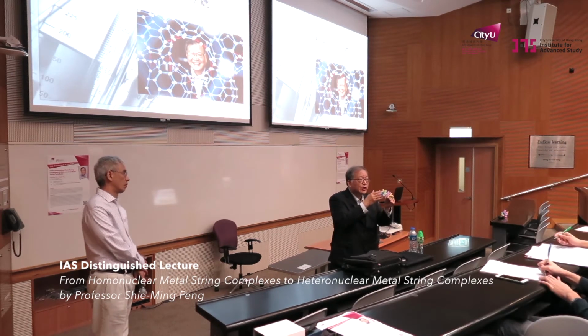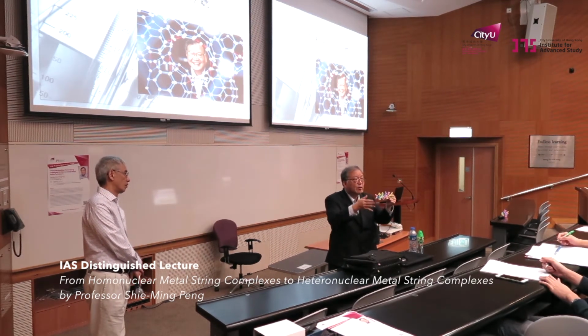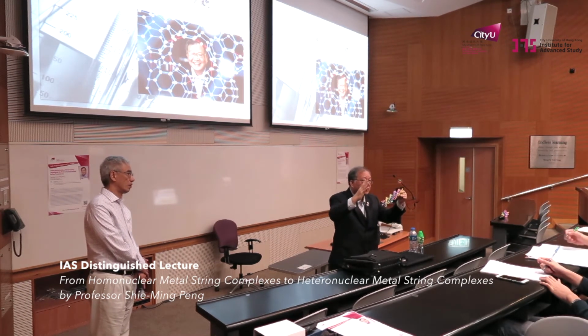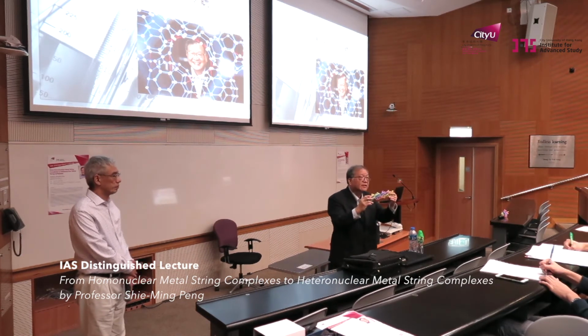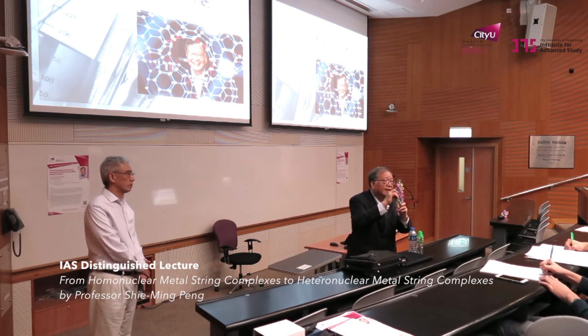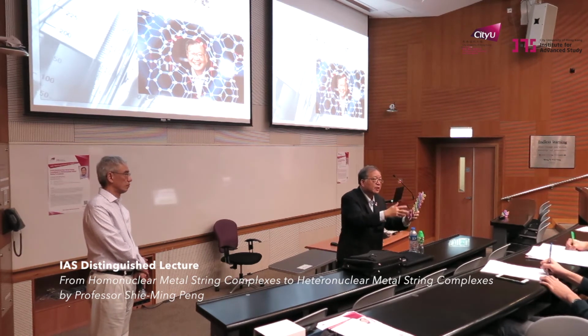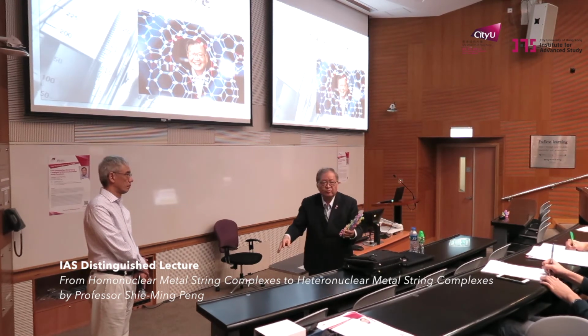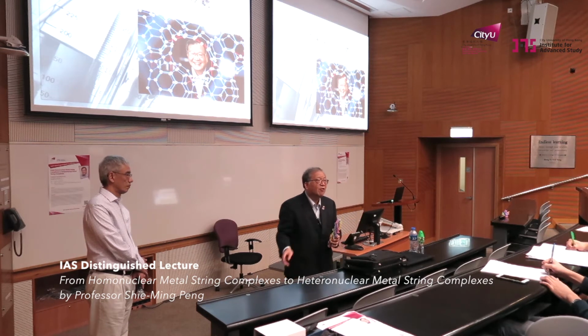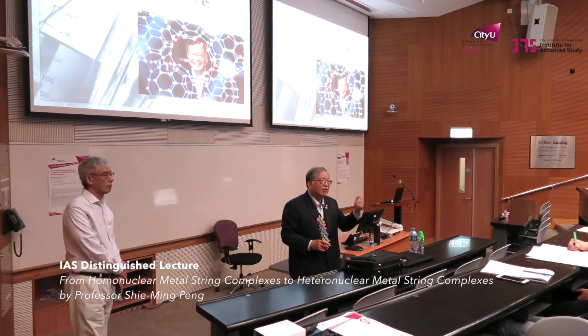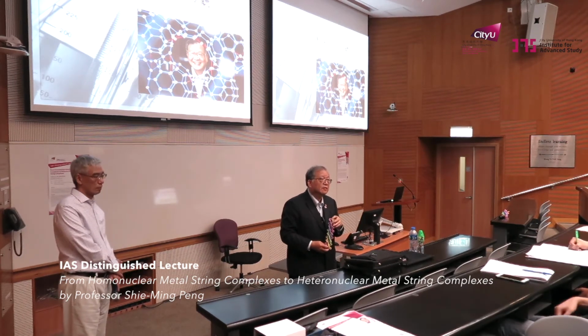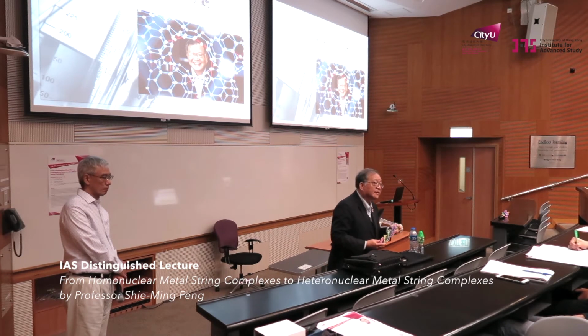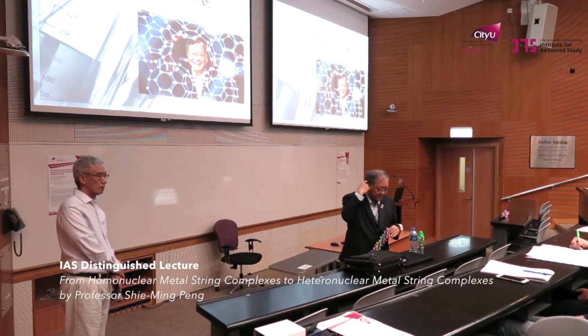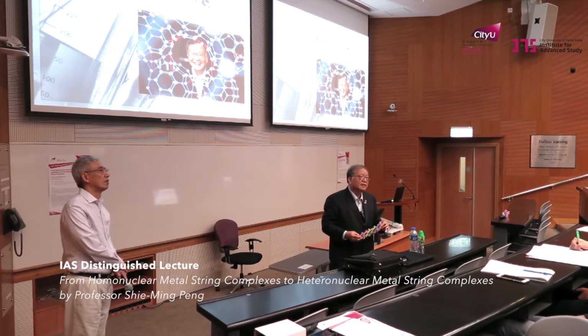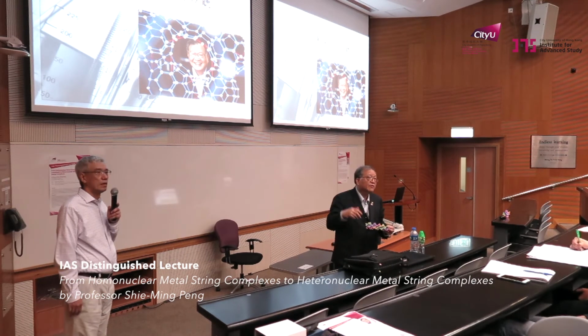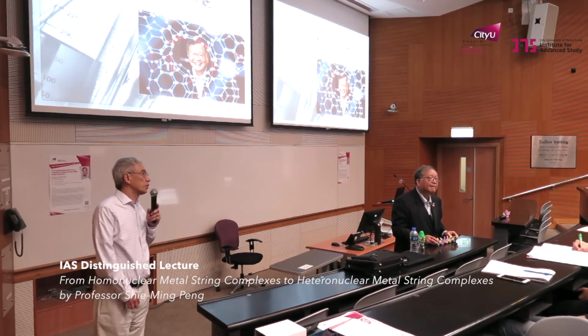Although there's no nickel-nickel bond, each nickel is square planar and can be squeezed by the ligand to get a closer distance, about 2.25. Like this one, the nickel-nickel distance is 2.25. And in our experience, from nickel to cobalt, the yield decreases to about one third. With other metals, it is even lower. This is just our experience, with no theoretical reason for it. So that is the explanation for the nickel metal string: most easily formed is the nickel metal string. Any other question from the audience?